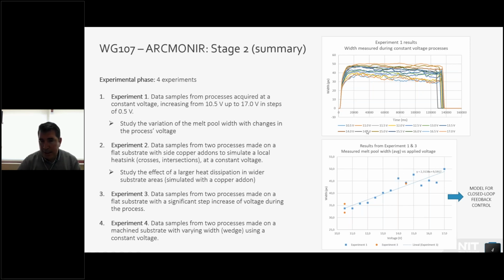The results of this experiment let us build the correlation that I mentioned in the previous slide, in which we can see the variation of the melt pool width as we change the arc voltage. Here you can see that we have a quite linear response, up to 14 volts. This will be the model that we will implement for the closed loop feedback control of the voltage.